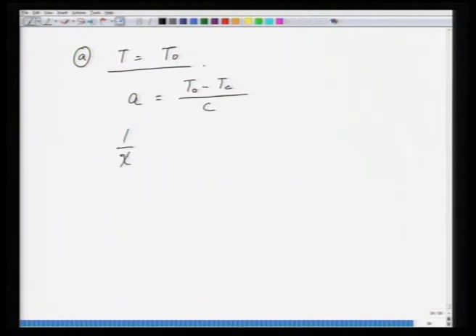So 1 over chi becomes a over T naught minus Tc divided by C, and this is for T equal to T naught. So this is the expression you get for the first order transition in ferroelectric crystals.